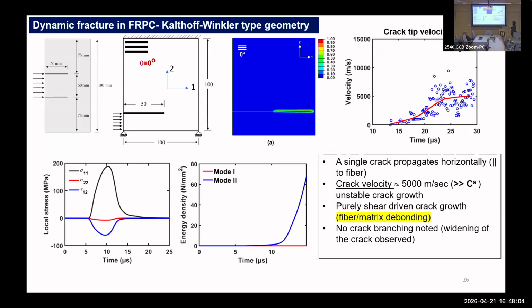If we try to characterize the crack propagation velocity by tracking the tip as it moves, then we see that 5,000 meters per second is probably the unstable crack growth velocity, which is way higher than the shear wave speed in this particular composite. So yeah, we did not see any branching.